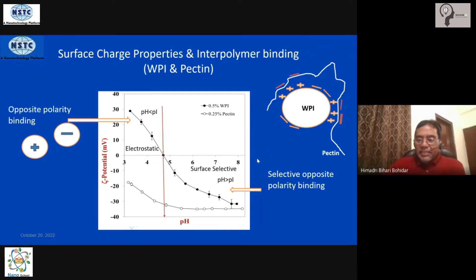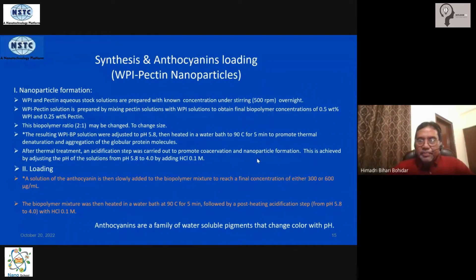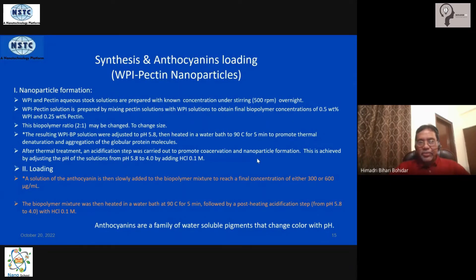Now we will see how nanoparticles are formed in this process. This is the exact step-by-step synthesis protocol. First, make a stock solution of both biopolymers, stir overnight to make them homogeneous and optically clear, then mix them at a certain ratio — in this example, 2:1, using 0.5% by weight of protein and 0.25% by weight of pectin. The protein-to-pectin ratio can be changed to control the particle size.